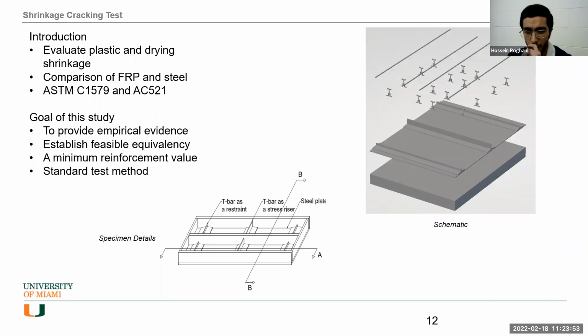We have started with the general guidelines of ASTM C1579, which evaluates the plastic shrinkage of FRC, which is a concrete that has fibers inside the mix. It's not the rebar or reinforcement. It's just some fibers. You can put them inside your concrete mix, as you have your sand, you have cement, or everything in your concrete. So there are some fibers, and we call them FRC. The general guidelines cover such things as the conditions of the restraint, moisture loss, concrete clear cover.